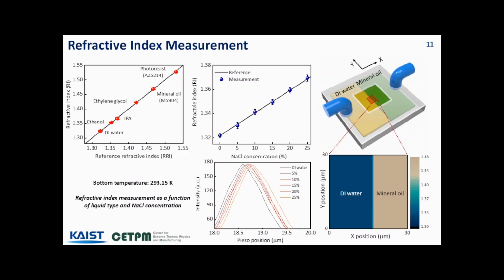Additionally, we measure the refractive index of DI water as a function of sodium chloride concentration at room temperature, below the saturation level. As shown in the graph at the bottom center, the third peak of the interferogram shifted according to the varying NaCl concentrations, allowing us to measure the refractive index. The refractive index of NaCl solution at different concentrations exhibits a linear relationship with concentration, as shown in the graph, with a difference of less than 0.5% compared to reported values in the near-IR range.